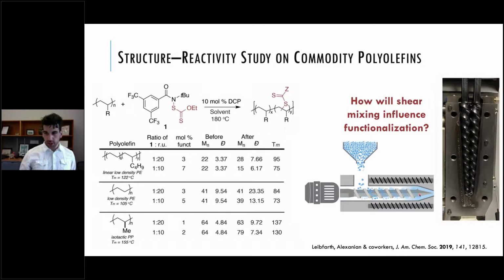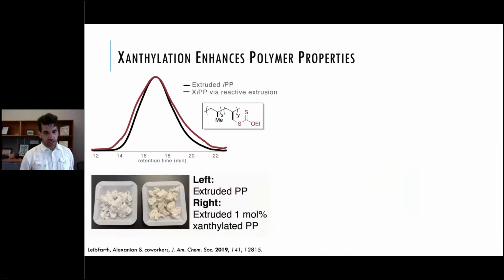I'm sure many of you are familiar with extrusion technology. This is how polymers are pelletized and processed industrially. This is a picture of our little lab scale extruder we have. And what you can see again is this is the polypropylene on the left that we put through the extruder. This is our material on the right. So what we did is we added this chemical functional group onto the polymer.